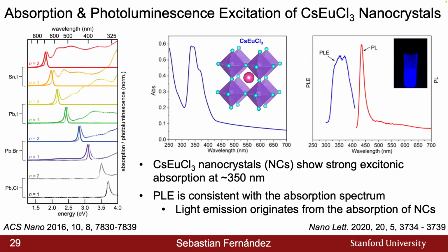Additionally, from these materials, again, for those that work within the space, we know that nanocrystals are a little bit more difficult to synthesize than the more simpler nanoplatelet synthesis that we've shown previously within here. They were able to achieve PLQYs on the order of 2 to 5.7% with additional treatments. And so this kind of guides the rest of the section here.